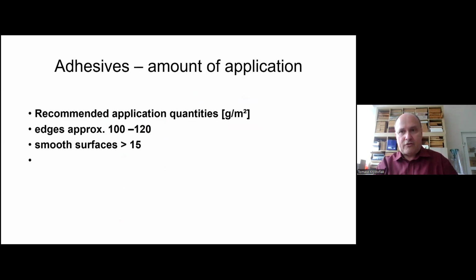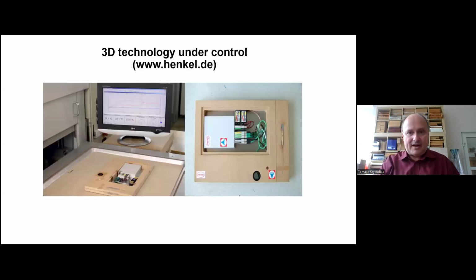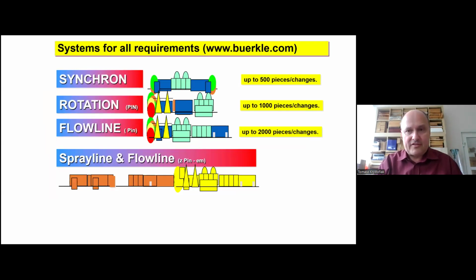Recommended amount of application, a very important factor, for edges between 100 and 120. For the rest, we can use only a small amount of our adhesive. On this place, you can see for control a special system from the German adhesive producer, Henkel. You can put material inside and put it into the press, and under control are temperature, relative humidity, moisture content, and on the screen of our computer, we can see the parameters.